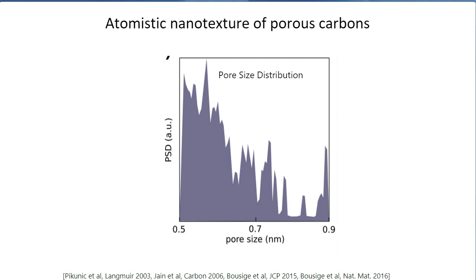Next, those porous carbons are porous. Looking at the pore size distribution, you can see they span a region between five to nine angstroms — mostly around five to seven angstroms. This means that when it comes to storing ions and water, those pores cannot have too many occupants — probably one water molecule, maybe two, or maybe one ion. We don't expect much of a bulk phase in those pores.